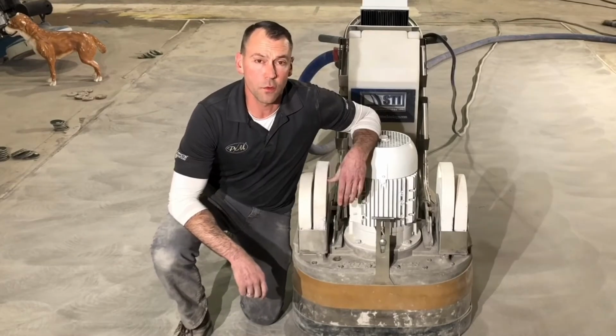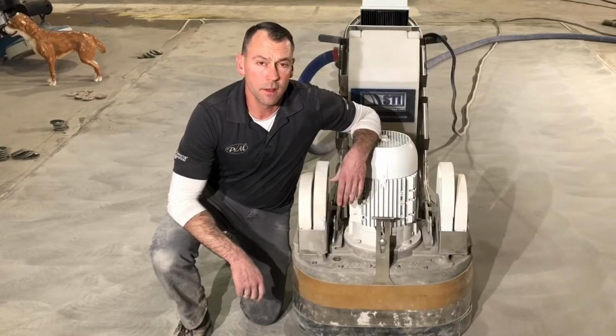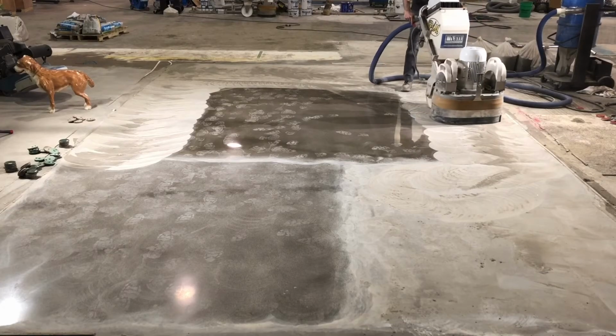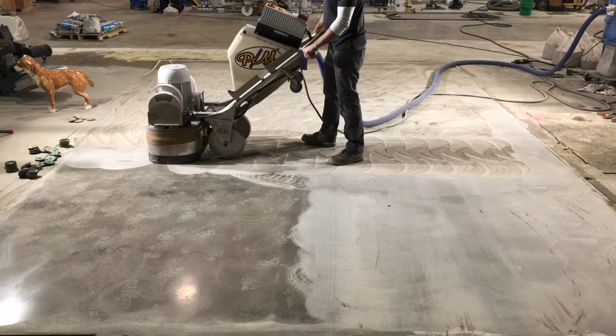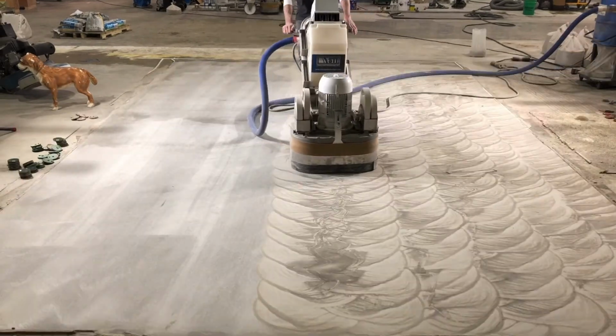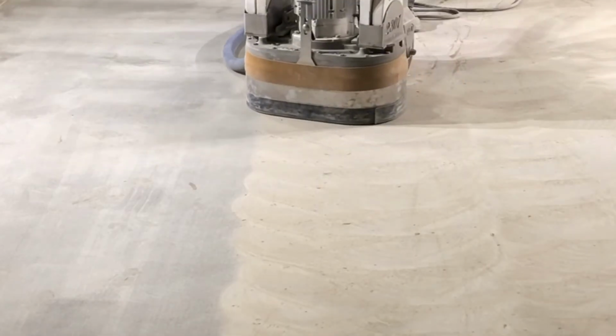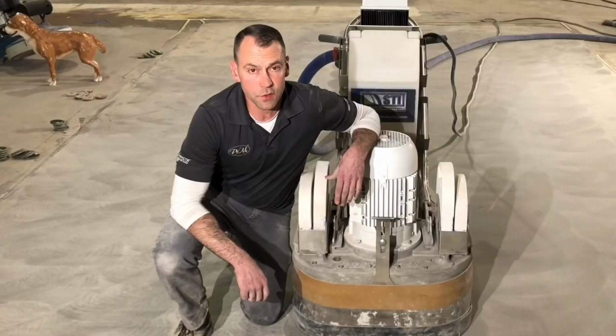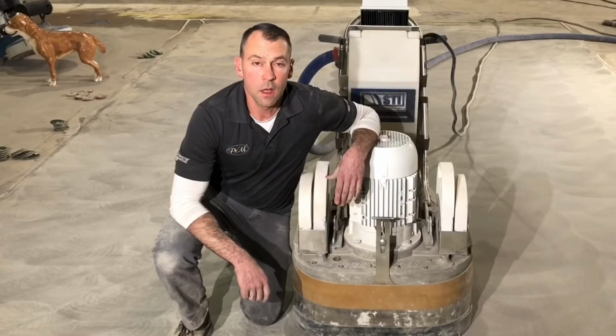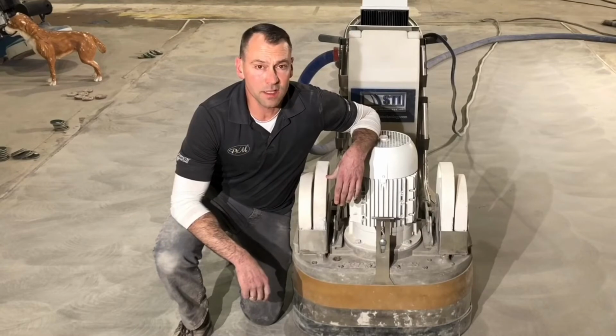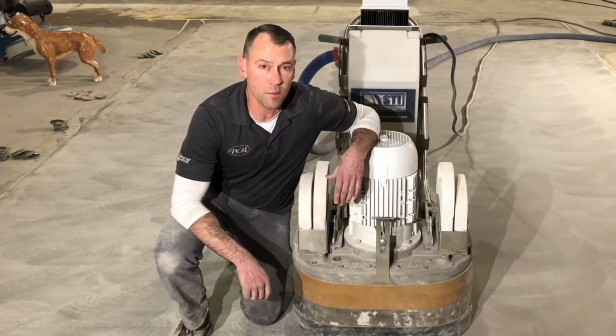Being that the floor is going to be exposed when it's polished and any color variations will be seen, the objective then became to grind through that surface until we had uniform color. This took a lot of grinding, 6 steps of grinding with the 16 grits, crossing it up each time to remove the discoloration. At the same time, being very cautious not to focus on any of the colored areas because the more we dig in one spot, the more we're going to affect the flatness of the floor.